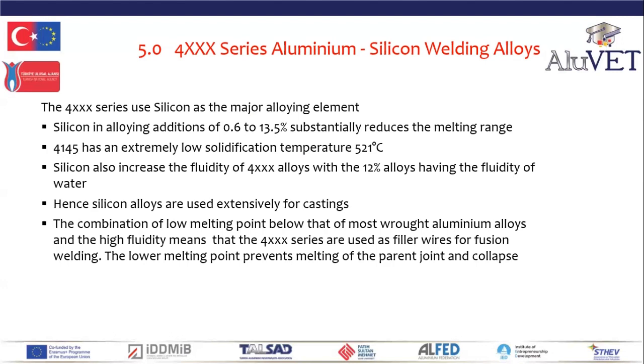So the metallurgists developed the 4000 series, which use silicon as the major alloying element, in additions from about 0.6 to 13.5%. So quite large alloying additions of silicon. Silicon substantially reduces the melting range. For example, alloy 4145 has an extremely low solidification temperature, 521 degrees C, compared to pure aluminium at 660 degrees C. So by alloying aluminium with silicon, the 4000 series have low melting temperatures, much lower than pure aluminium or other alloys.